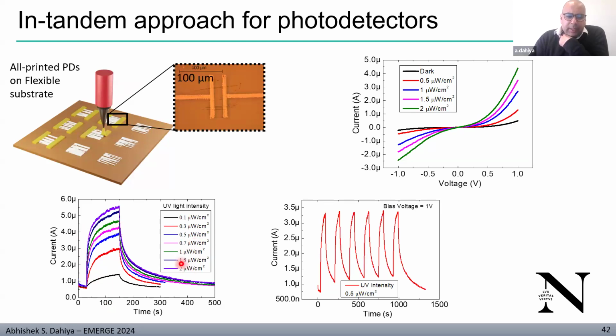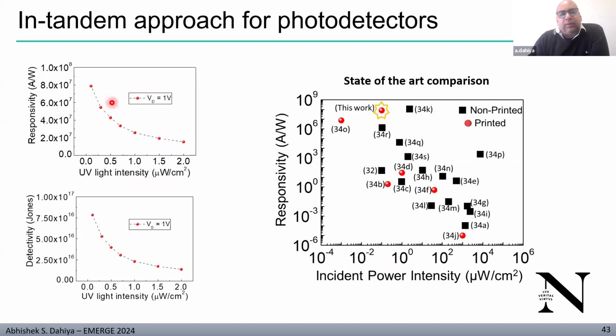Under increasing UV light, the on current is increasing, and this is a repeat of the cycles we have done at a bias voltage of 1. The extracted responsivity was impressive. Here we have compared with most of the printed and non-printed state of the art, and the peak responsivity we could achieve under very low light intensity was impressive in this case.